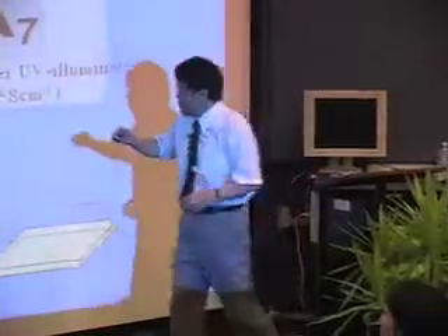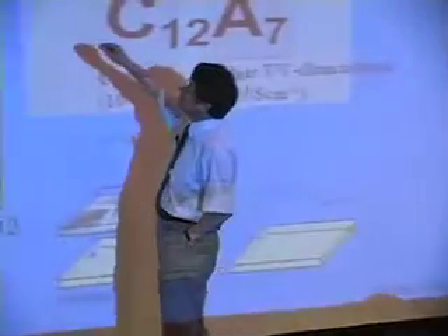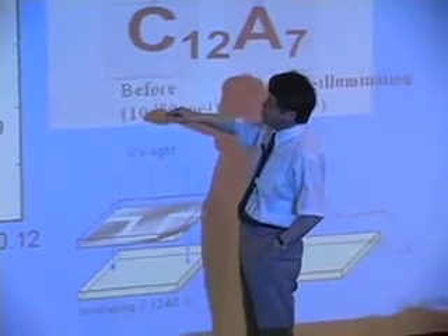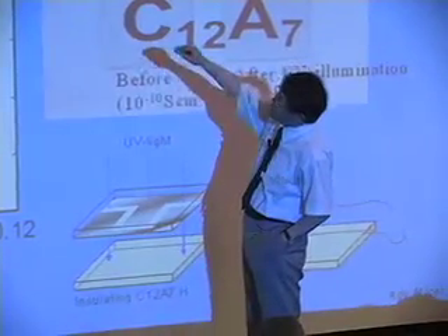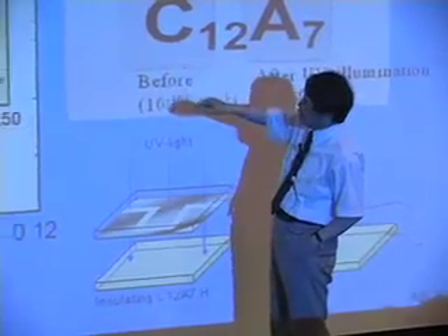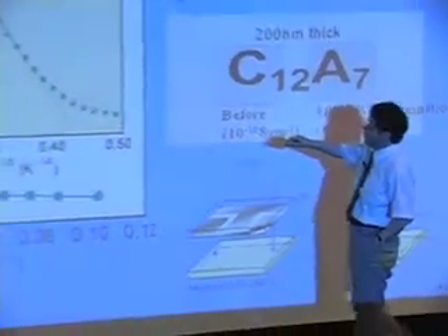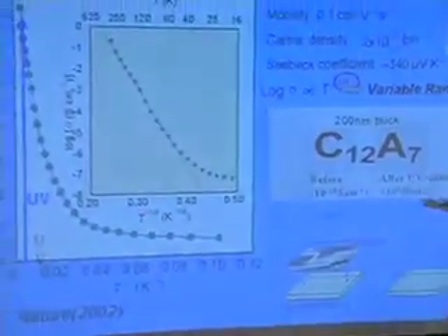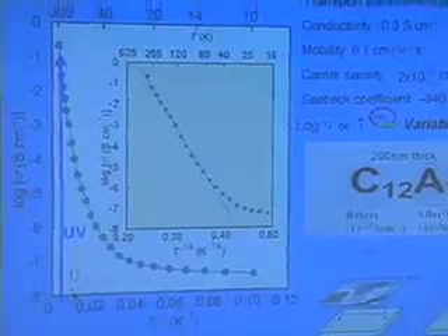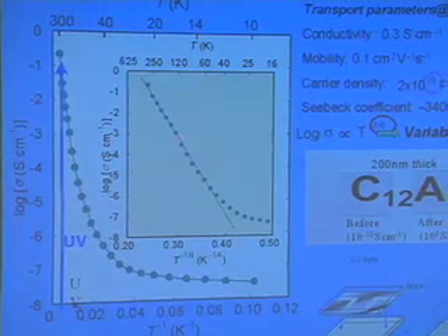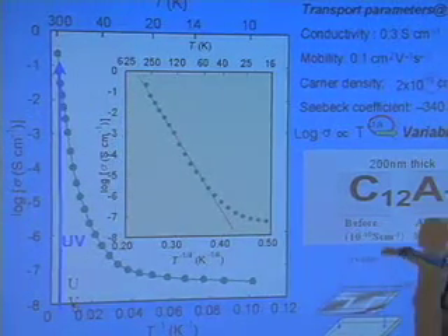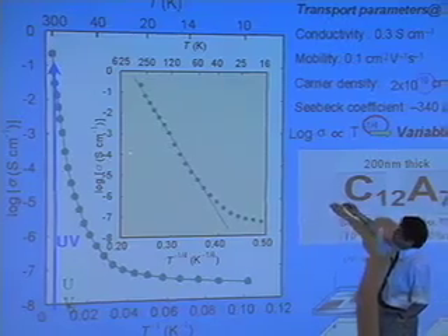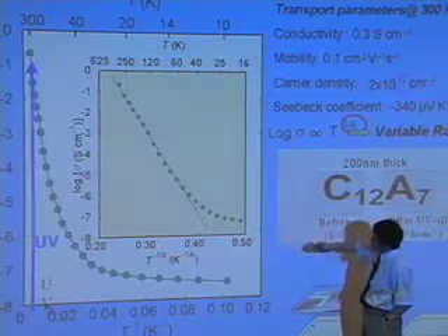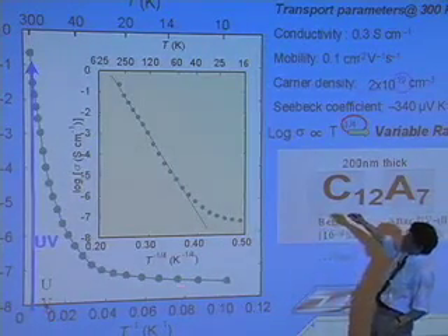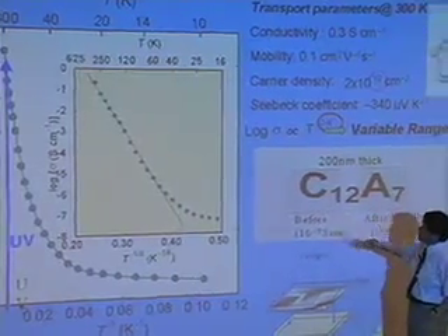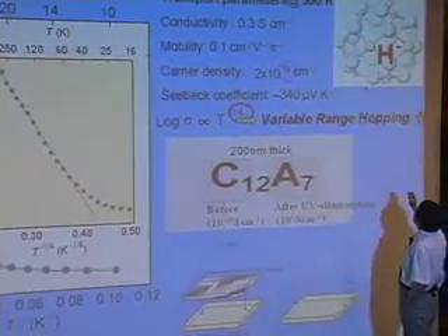This is the temperature dependence of the conductivity. It's not linear like this, but almost linear as a function of T to the quarter power. This means the conduction mechanism is not a thermal hopping type mechanism, a simple Arrhenius behavior, but rather variable range hopping.